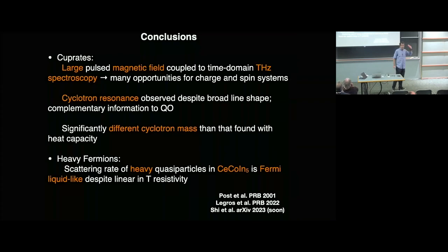These experiments could not be done, I think, any other way than the way that we've done them now, other optical experiments, other ways of doing magnetic field. And we observe a cyclotron resonance despite the broad line shape in the scattering rates. And these kinds of experiments give complementary information to quantum oscillations. Significantly different cyclotron masses are observed in the scattering rates than found with heat capacity.